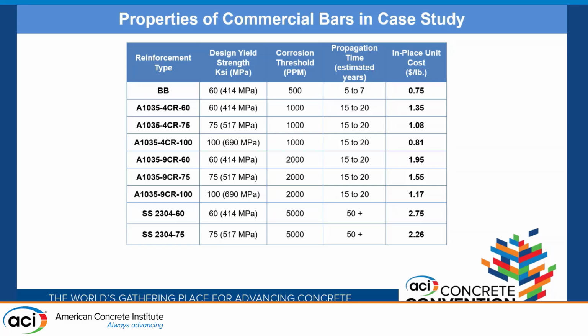Now, if you look at the A1035 with the 4% chrome, it has a higher tensile strength, which I showed before. The yield strengths are much higher, so you can use it as a 60, which is basically the same as the control bar. You end up with a higher threshold value, because it's not as good a cathode. It takes longer for it, the propagation's longer, and the price ends up being, on a direct basis, $1.35 a pound. However, you start taking advantage of the strength and can use it as a 75 or a 100 grade.